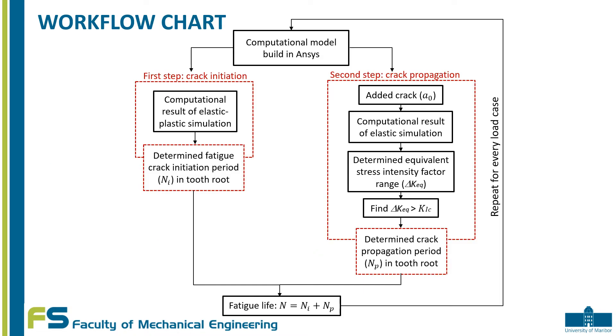Here you can see the workflow chart. The computational model was built in the ANSYS program package. In the first step, the fatigue crack initiation period in the tooth root was determined based on computational results of the elastic-plastic simulation. In the second step, the crack propagation period was determined based on the initial crack, computational results of the elastic simulation, and finding the equivalent stress intensity factor range larger than the critical stress intensity factor. Total fatigue life was then calculated from the equation below, and every step was repeated for every load case.